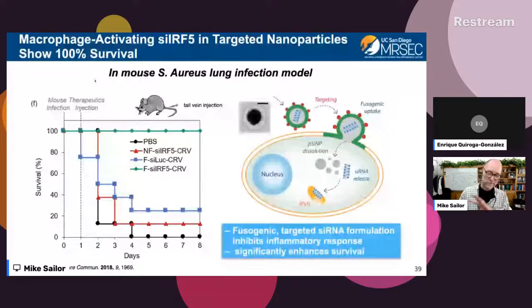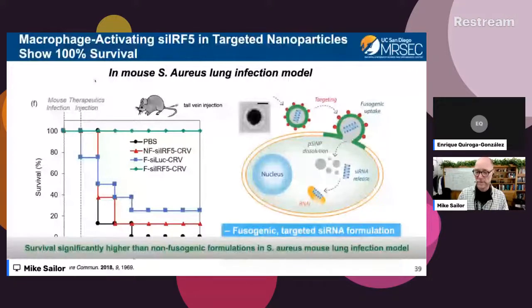So kind of long story short, in the end of the day, we found that these nanoparticles can target the cells very effectively. They can shut down that inflammatory response. And when that inflammatory response was shut down, now the mice have their own immune system being able to kick in and fight off the infection. And so at least in this model of infection, a Staph aureus lung infection model, we were able to completely rescue all the mice just by slowing down that macrophage overreaction.